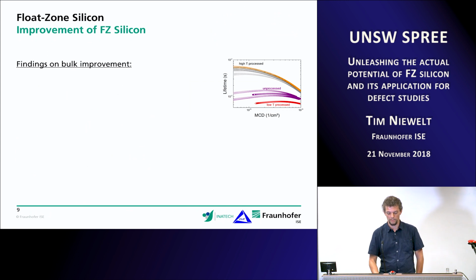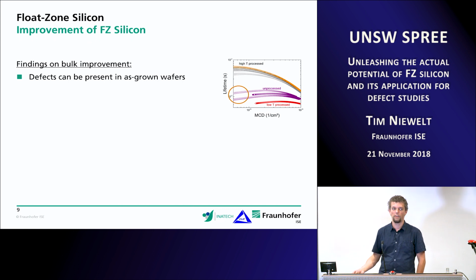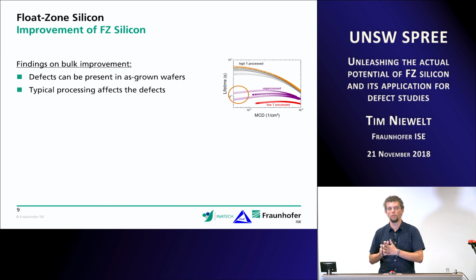So let's summarize some of the findings from this type of experiment that we've done over and over. We see that in unprocessed wafers, in as-grown wafers that we just take directly out of the box and do experiments on, we sometimes have these defects, and they can affect the experiment quite a lot, because the lifetime can be really, really bad in comparison to what we would expect it to be. Then we've seen that typical processing does affect the lifetime of float zone silicon wafers. A POCl3 diffusion is actually improving the wafers a lot, and oxidation usually improves it a lot. And then there are even some processes that kill your wafers. Basically, I've seen single-digit microsecond lifetimes on float zone wafers. That's not how they are supposed to be.